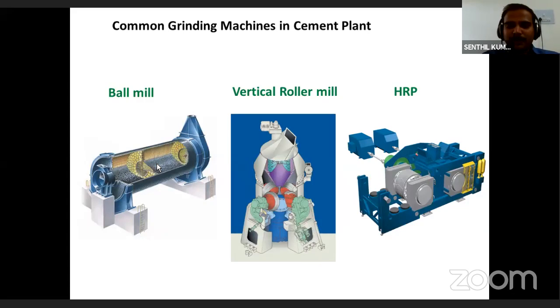So the wear rate also depends on several factors. Grindability is one factor. If I get a different material whose wear rate is more than the normal one, then the media wear will be on the higher side. And if a higher moisture material comes inside, then also my wear rate will go up.